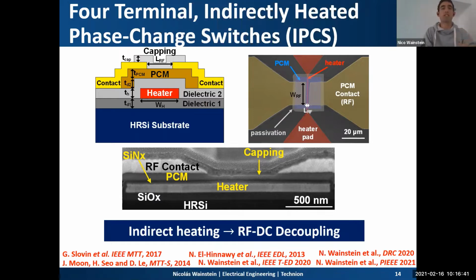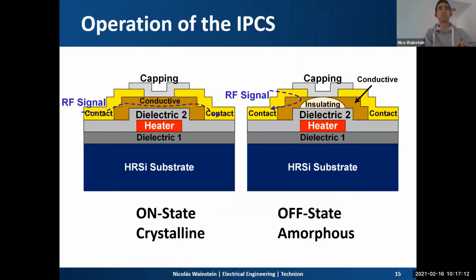So far, the germanium telluride has been the material of choice for RF applications due to its low resistivity in the crystalline phase and relatively large resistivity contrast with the amorphous state. Here you can see some SEM top view of our devices and a cross-section of the fabricated devices. You can see the different layers and how the heater and the PCM are isolated by a thin electrically isolating layer. So let's see how the IPCS works.